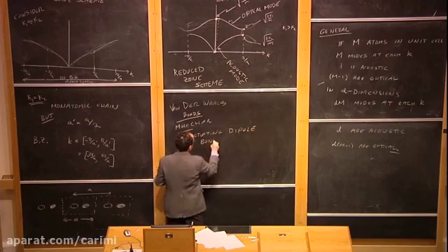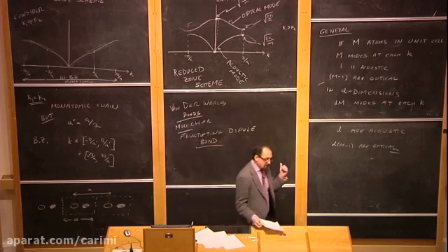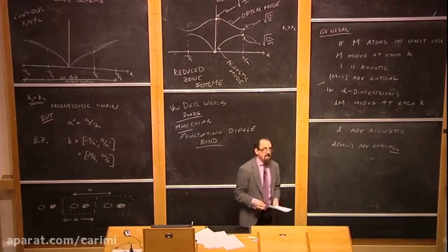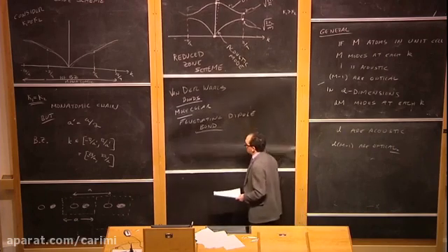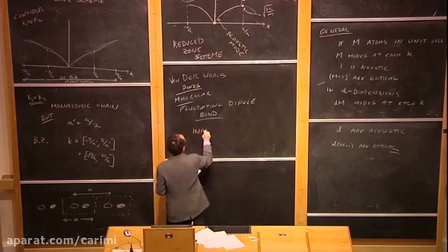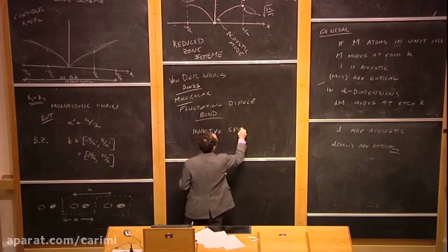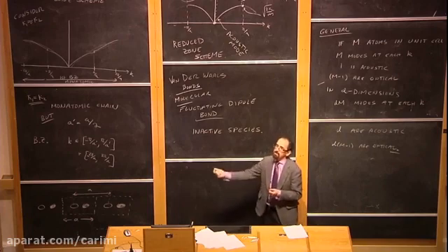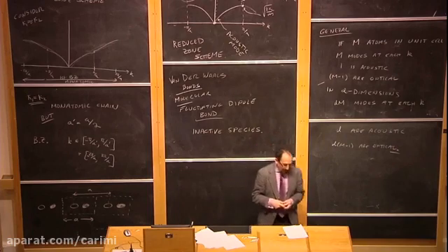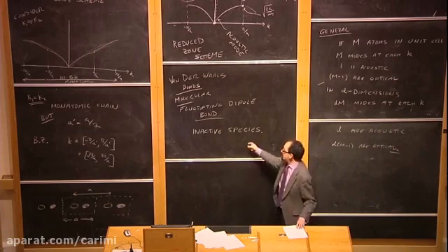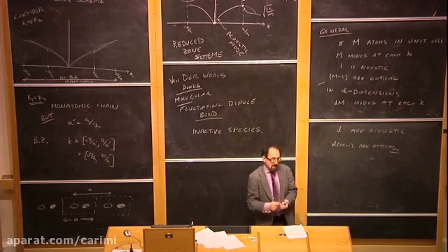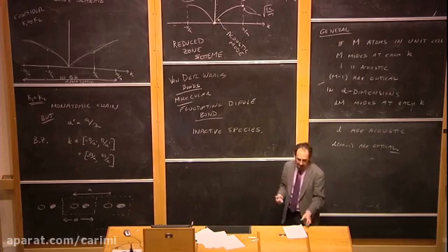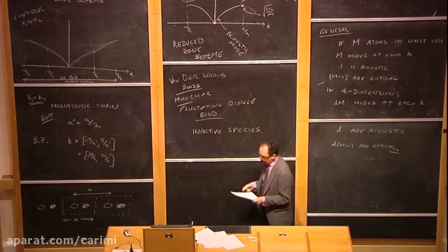These van der Waals bonds are actually quite different from either ionic or covalent or hydrogen or metallic bonds in the sense that these bonds occur for inactive chemical species. And what I mean by inactive species is that no electron is transferred between atoms, no electron is shared between atoms. Things like noble gases are classic cases of van der Waals bonding. The noble gas has a filled shell. It doesn't share its electrons. It doesn't donate its electrons. It doesn't covalently bond. It doesn't ionically bond. But it can still van der Waals bond.